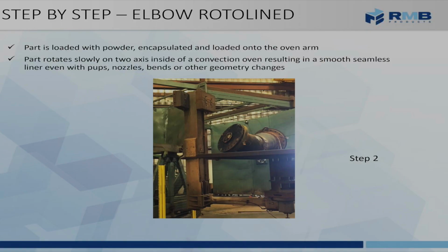Once we've done the surface blast, we put the resin in, in granular, powder form. We close it up, we put it on an arm and put it into the oven, into the temperature that's going to melt that resin. And as that part rotates, that resin flows and covers all of the internal surfaces, including onto the flange faces where there would be wetted surface.